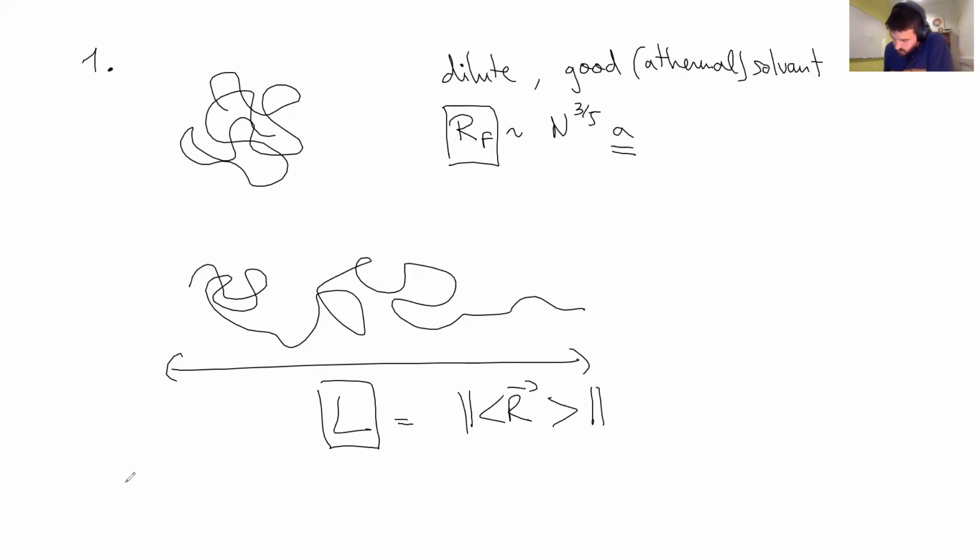And finally, you have the force. To construct a length scale, the third one is, if I do a ratio between the thermal energy and the force, this is the typical length scale associated with the force that I can construct. Let me call it D. And these are the only 3 length scales I have in the problem: the undeformed size, the deformed size, which is my real observable, and the amount of force versus thermal energy. So this defines another length scale.